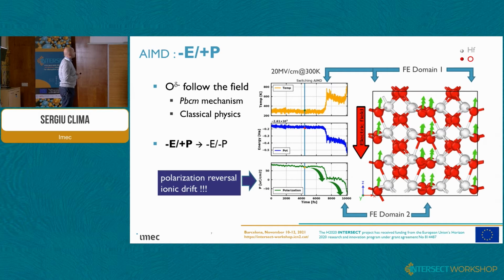The problem with this mechanism is that afterwards it goes over a smaller barrier, so the oxygen will shift in between the domains, and this mechanism will lead to ionic drift. So these oxygens will go up, up, up, and up. And actually, after this data point, which I did not go beyond, we get complete meltdown and dielectric breakdown and melt of the material because the temperature goes way too high. But this is because I chose a very high electric field for this high barrier to see it switching.